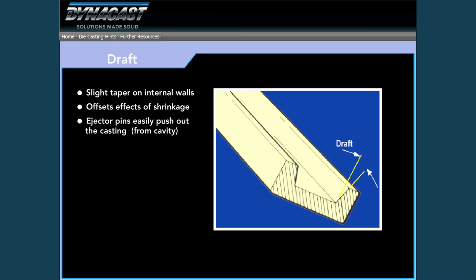Again, we talked about the wall sections. You see on the very bottom there, down to about 15 thousandths. We can actually get down sometimes to 8 to 10 thousandths in certain areas also. Core draft angles, you can go back as minimal down to 0 degrees for very short distances, and then say 1.5 to 2 degrees thereafter from a casting standpoint.